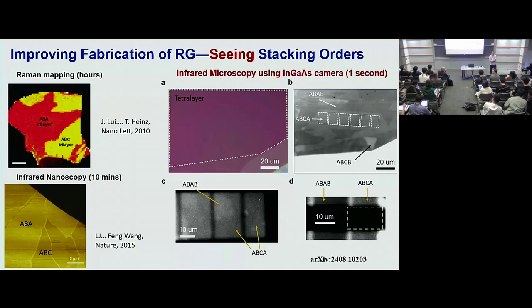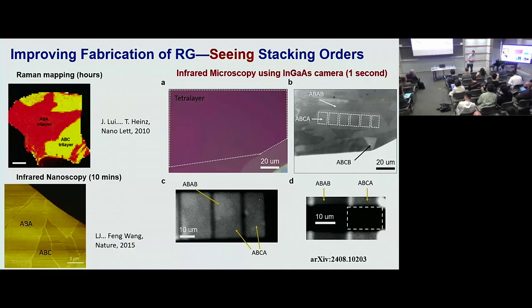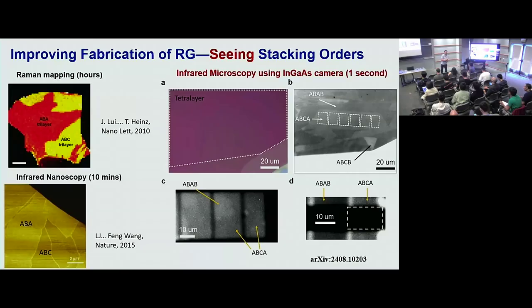In all of those 3 samples, you don't see any integer Chern insulator, right? In all the unaligned samples. Not yet. Well, what's the region of parameters that you've tested compared to the aligned samples? I think we probably covered... What do you mean by not yet? A big enough n-D map. But we have other samples like 5 layers, 6 layers that we're still testing now.